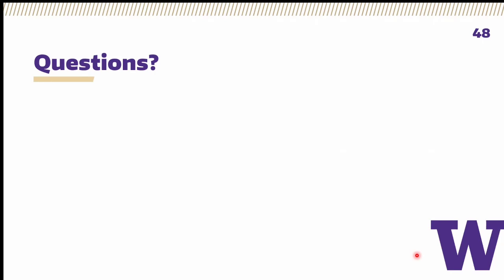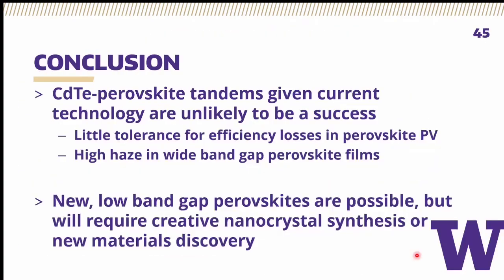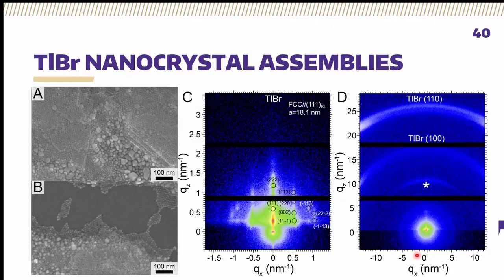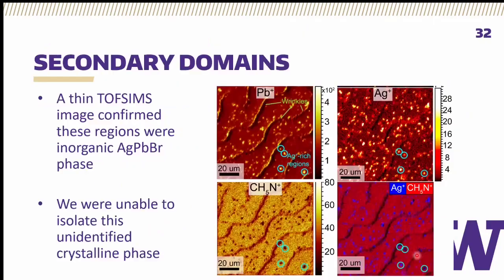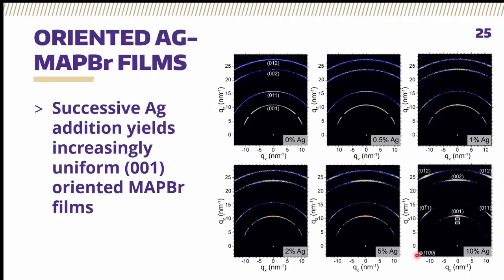Can you talk a little bit about it was almost like a wide angle XRD, but it had the azimuth technique. That's not one I'm familiar with. Can you talk about it a little bit more? Yeah, so it's easy enough to see. The way you would observe crystal texture normally is you just look at this peak and you see if there's a spot versus a ring. If there's a ring, you have this random uniform texture.